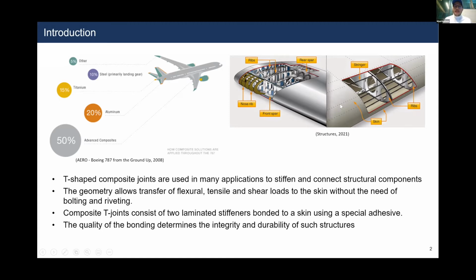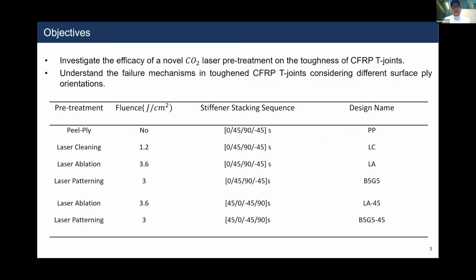So as an initiative to employ more non-metallic materials and employ composite materials in the aerospace industry, many studies have been going on CFRP and composite T-joints, which consist of 2 laminated stiffeners bonded together to a skin using a special adhesive. However, the quality of the bonding determines the integrity and durability of these structures. So there are many toughening techniques, but my study focused on investigating a novel carbon dioxide laser pretreatment technique on the adherends of the CFRP T-joint to improve the toughness. I also wanted to understand the failure mechanism in toughened CFRP T-joints considering different surface ply orientations.